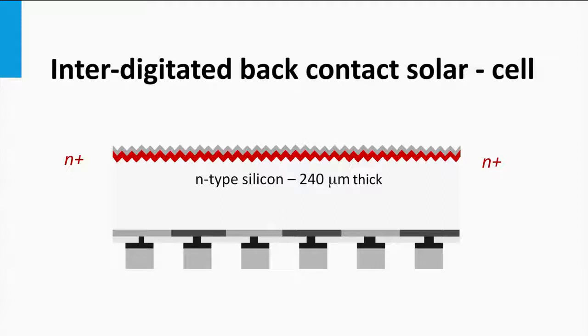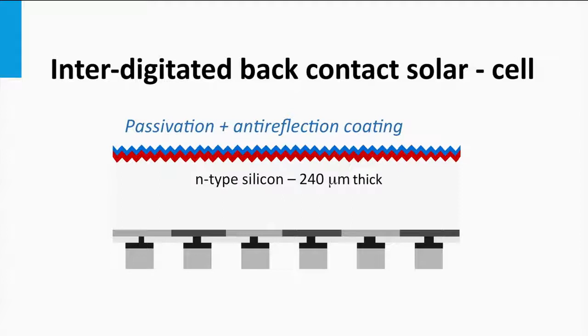The front surface field behaves like a passivation of the defects at the front interface and allows to have higher levels for the minority densities in the bulk. At the front side, the reflective losses can be reduced using the same tricks as discussed for the PERL solar cell: deposition of double-layered anti-reflection coatings and texturing of the front surfaces.